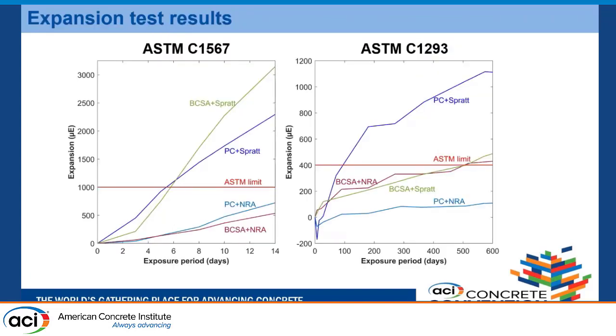So here are the results of the expansion test. Let's start with the accelerated test, which is on the left. The plot compares the exposure period and the expansion. By expansion, I mean the length change as a result of the test. For the accelerated test, you have an ASTM limit, which is 1000 microstrains. The specimens which cross the mark in the test period are considered to be ASR reactive.